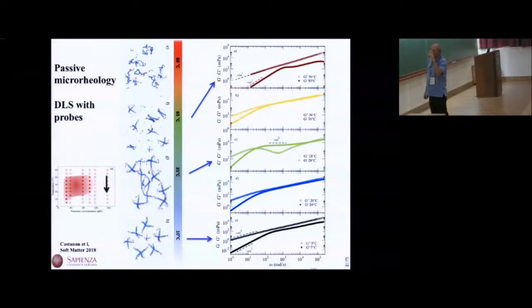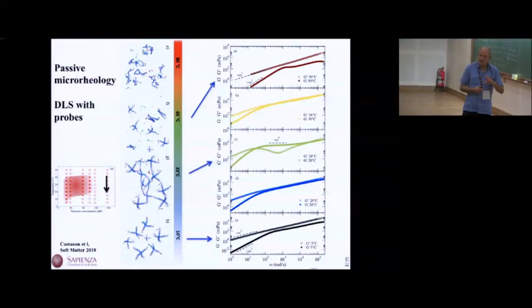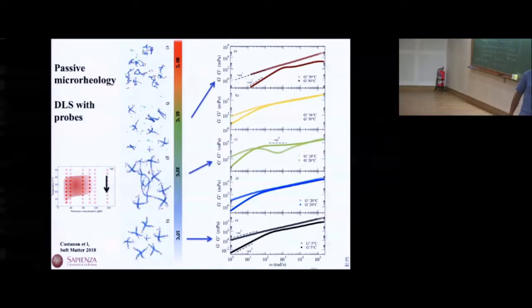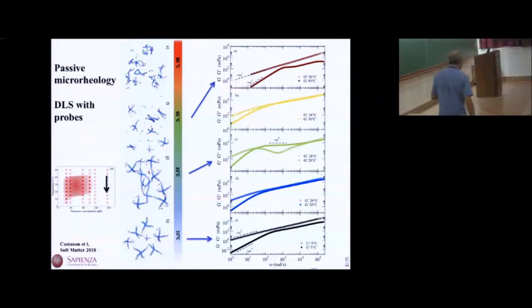So we put particles, colloidal particles, in the sample, and those particles have a larger refractive index, so the scattering of those particles is dominant compared to the scattering of the DNA. Actually, the DNA doesn't scatter too much, so it's very easy. So you see only the scattering of the probe particle, even if you put a very tiny amount of them. But let's say packing fraction 10 to the minus 4. This is the order of magnitude. So you really see the self-motion of those colloidal particles.